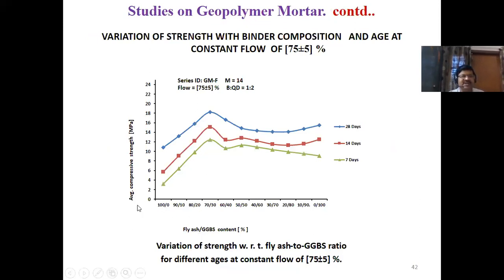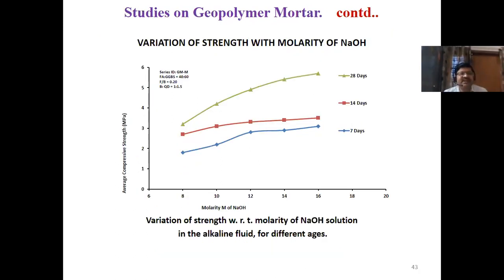With the fly ash and GGBS content at the given age. Average compressive strength. See here, as the GGBS content increases, strength increases, and of course comes down. So that means at this point there will be maximum strength. That means in case of geopolymers, if you want to get maximum strength, the GGBS content should be around 20 to 30%. This is proved long back. We verified in the laboratories. Next, the variation of compressive strength with molarity of sodium hydroxide. So this is average strength and this is the molarity, right?